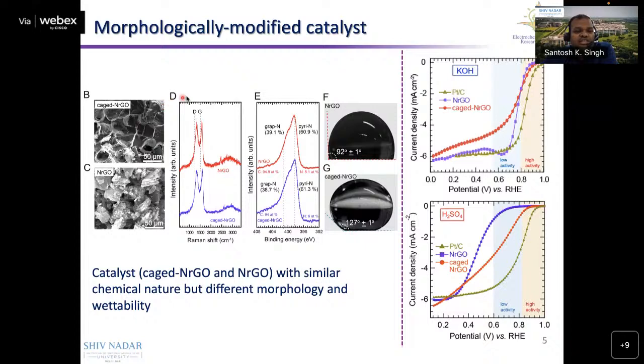And the chemical composition and chemical properties of these materials we checked by Raman analysis and XPS analysis, which showed that the amounts of pyridinic nitrogen and graphitic nitrogen are almost similar in both cases. So the catalysts have similar chemical properties, but different physical properties, like the surface tension of water. This is what we confirmed from this study.